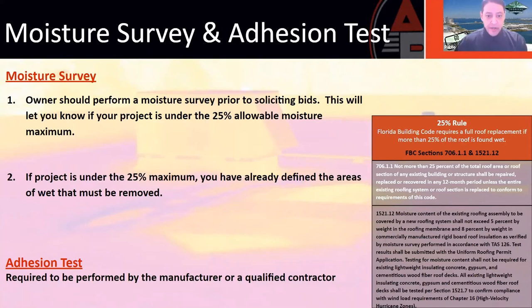Thank you, Clint. So now we're gonna talk about those moisture surveys. What we discussed earlier, that the initial roof inspection, qualifying the roof to see whether or not it would be a good candidate for roof coating. By the Florida Building Code, there is a moisture saturation content within a roofing surface that once you achieve that threshold, which is 25%, you wouldn't be able to coat, you wouldn't be able to re-roof, you would have to tear off. So if more than 25% of a total roofing surface is saturated, that's the threshold where there's not really much of an option at that point.